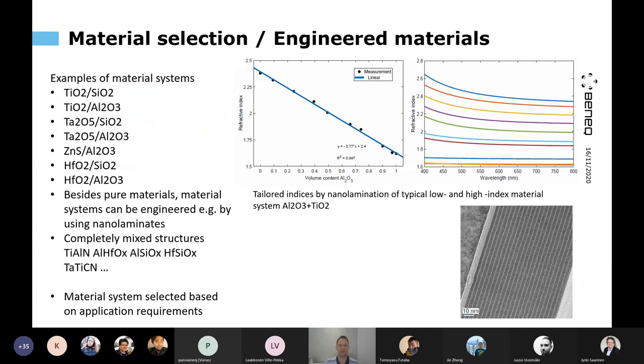ALD can also make very various different materials. So almost any oxide material can be deposited with ALD, and various other materials as well. So here some typical examples are shown. When making optical coatings, we normally use two materials at least, a high index and a low index material. The most common combination being a very high index titanium oxide and a low index silicon dioxide. But for different applications, we use also various other combinations, including titanium oxide, aluminum oxide, which is quite common, and tantalum oxide is also rather common material. Zinc sulfide is also a very good high index material, and some others, hafnium oxide also sometimes used.